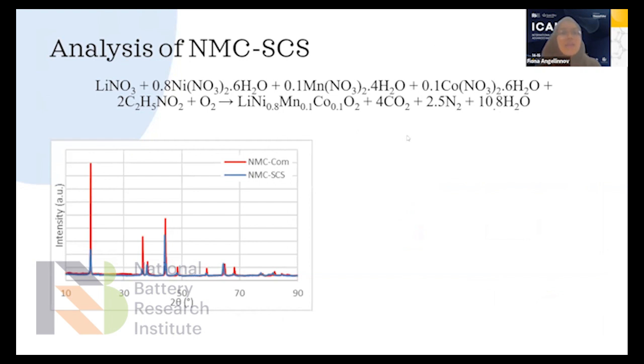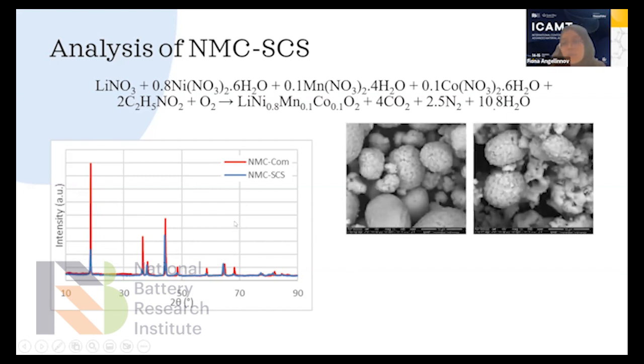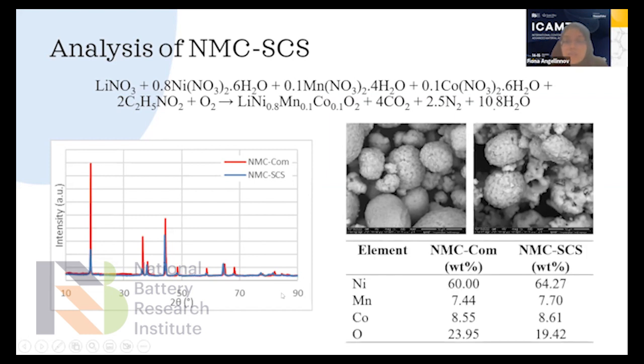And for the NMC-SCS, here's the reaction that took place when the solution combustion happens, and this is the diffractogram. We compared the NMC-SCS with the commercial NMC811. Here we name it NMC-Com. We can see that both have the same peaks at 2 theta, and both are crystalline. Further, we characterized it with SEM. The right one is the NMC-SCS and the left one is NMC-Com. We can see that both have a spherical shape, with EDS similar to each other for the elements nickel, manganese, cobalt, and oxygen.